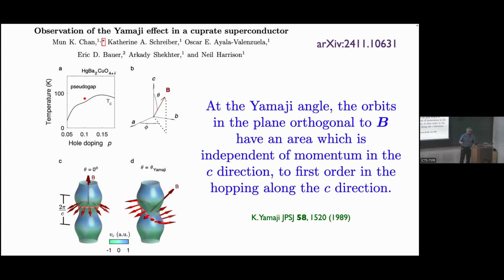If there's a flat band, you would expect the magnetoresistance in this direction to be very large, because there's just no tunneling along that direction. Okay, so that's called the Yamaji angle, and it's been observed many times in various two-dimensional materials, the organic materials, and